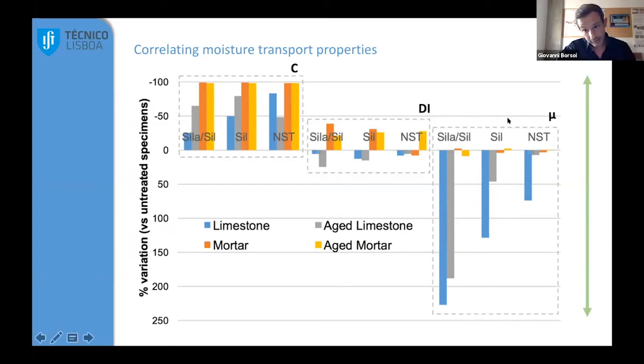At the end, we have also the water vapor permeability, and we can see that, for example, in the case of this siloxane-silane product, there is a huge decrease of the water vapor permeability, increase, sorry. And so for sure, this is something that we are not looking for. We're looking for something that is only slightly affecting this value, and so once again respects the properties of the original material.